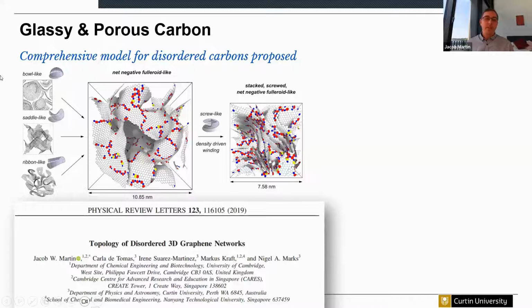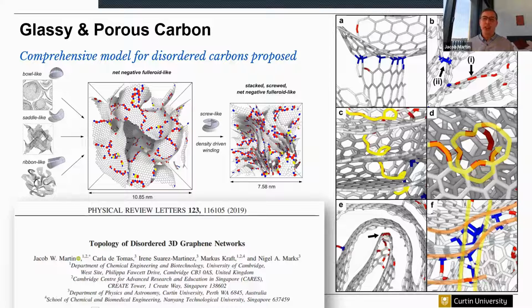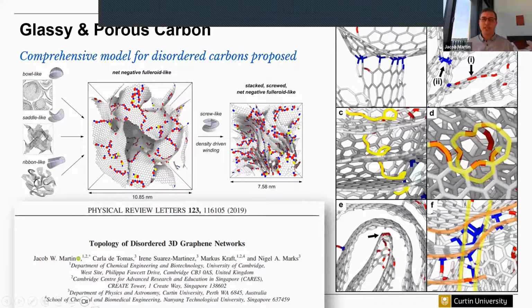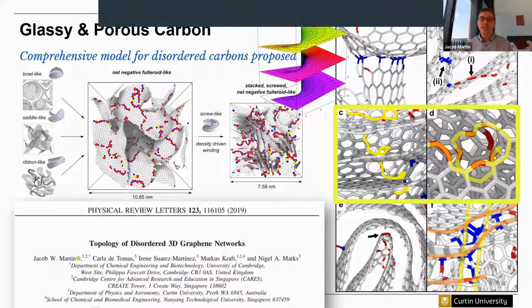And we found that they had this saddle-like shape, which is that foam topology. So it's actually a disordered 3D graphene is the way that we're describing it. But we also found a whole bunch of very interesting defective structures. And the one that I just want to highlight is we found screw dislocations.